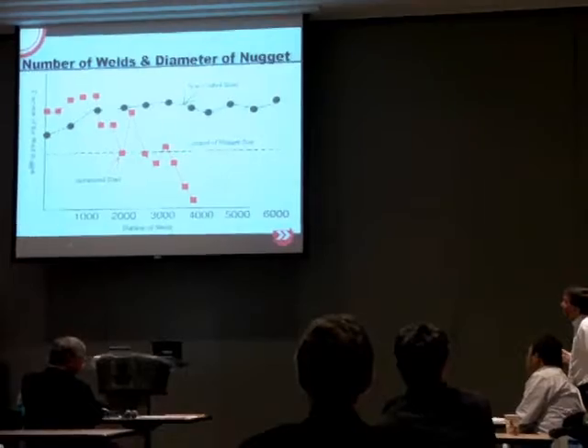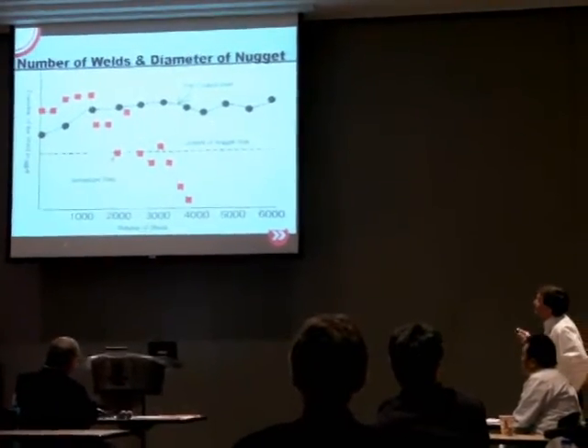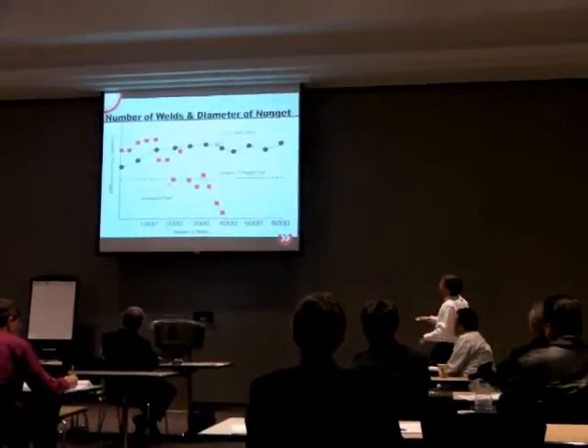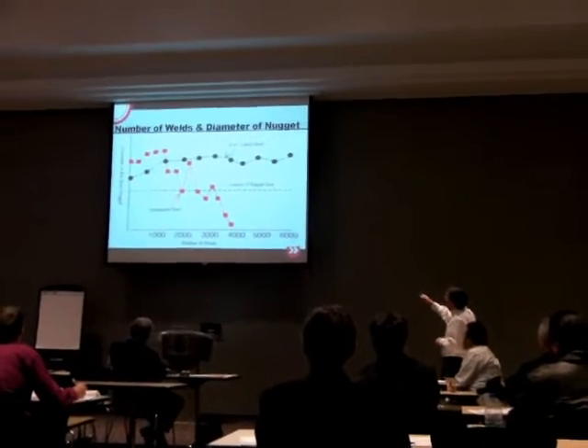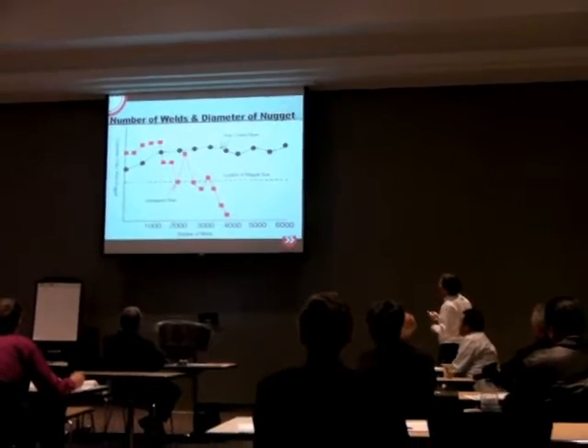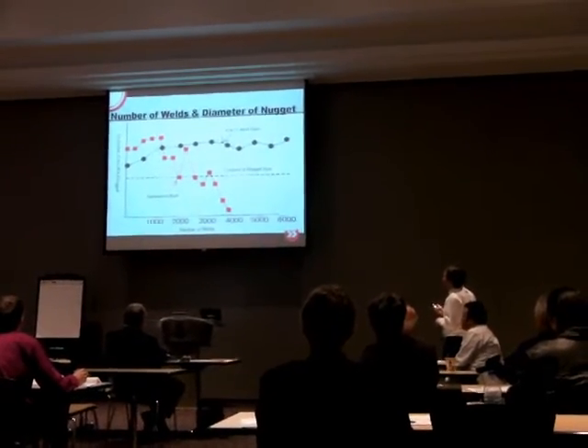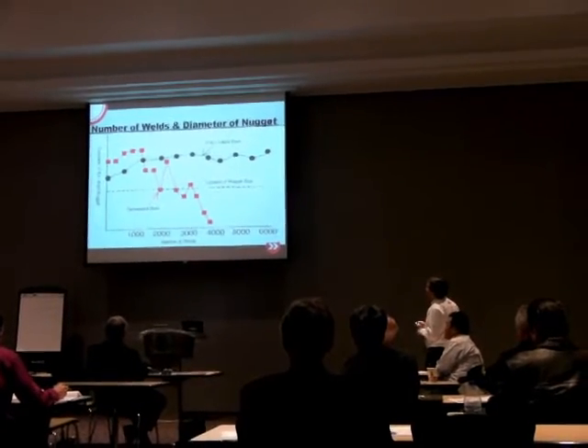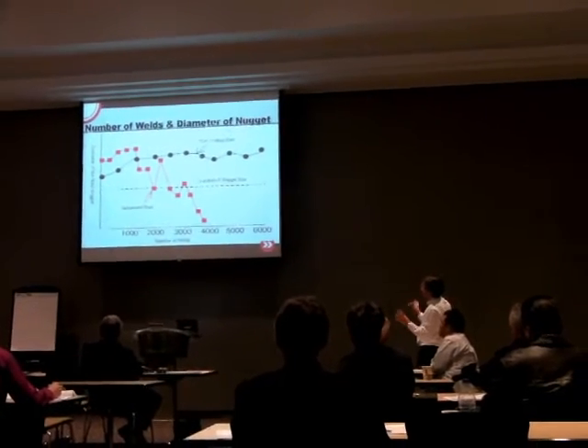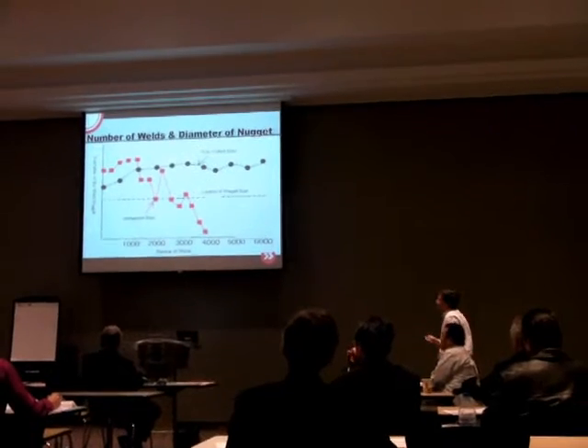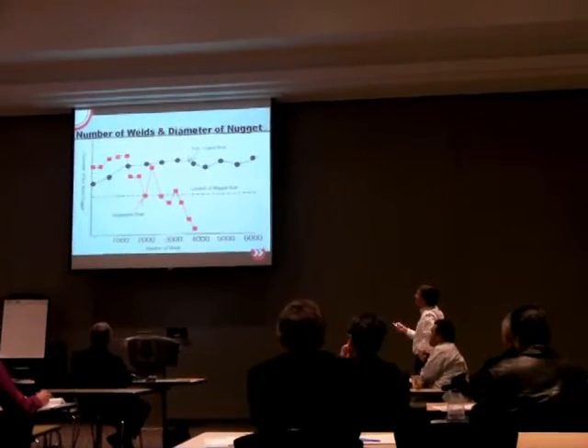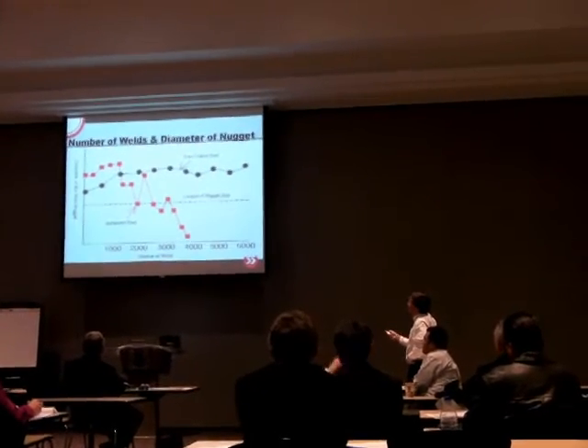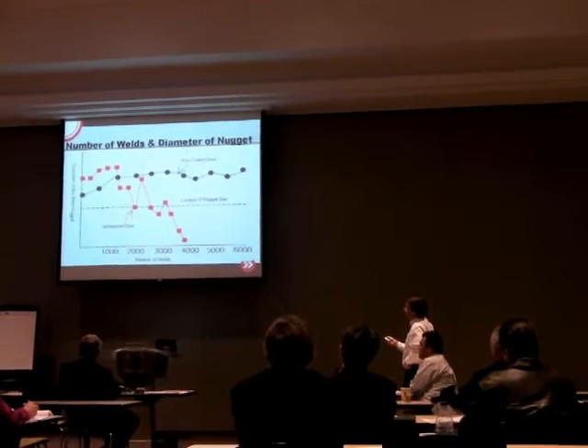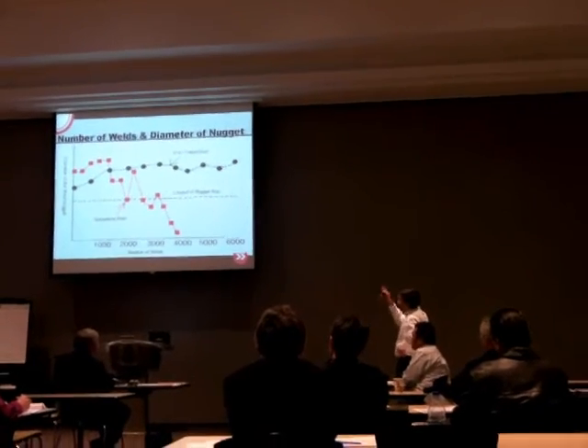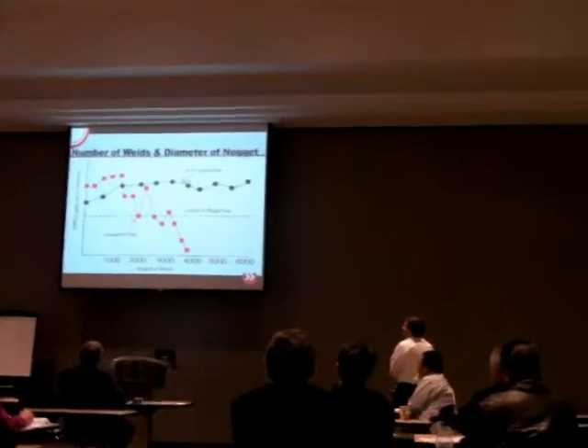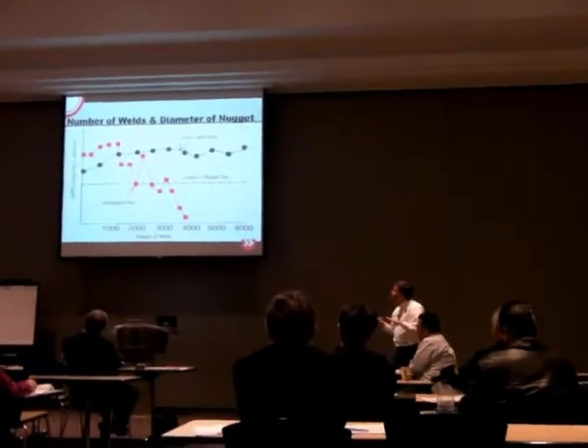This is a chart here where we're looking at the number of welds and the diameter of the nugget. Now, what we wanted you to see was when using non-coated steel, it stays pretty stable throughout. There's not a whole lot of change there. As the number of welds increase, the diameter of the nugget stays about the same. But with galvanized steel, after about 1,800 welds, you see it start to get really jumpy, like my hands are right now. You see it start to move all over the place. And that's what caused inconsistency.